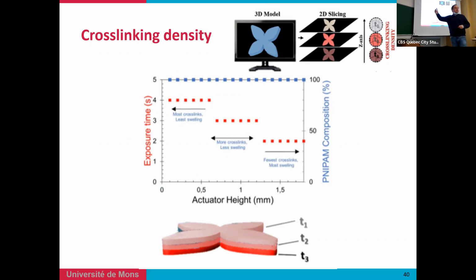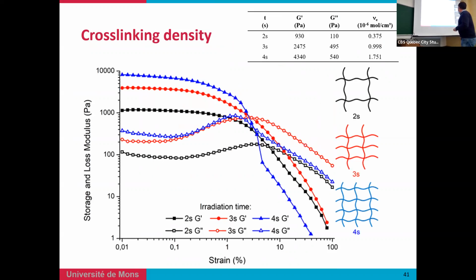If you use a short polymerization time, you have a less crosslinked system. When you use a longer polymerization time, you have a highly crosslinked system. Playing with that, you can create a gradient layer simply by changing the polymerization time.